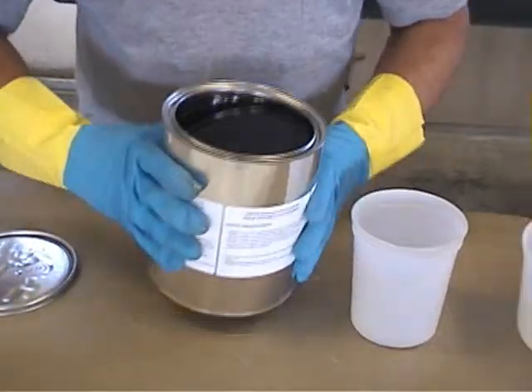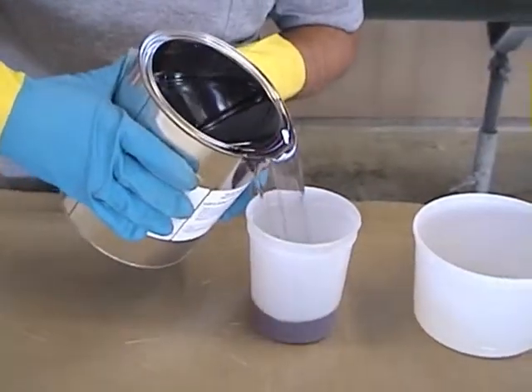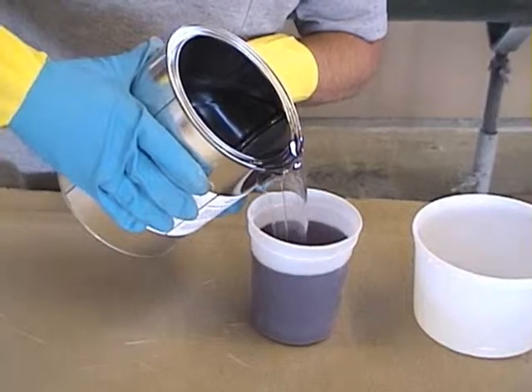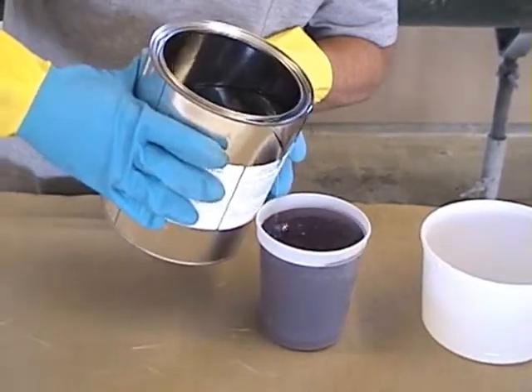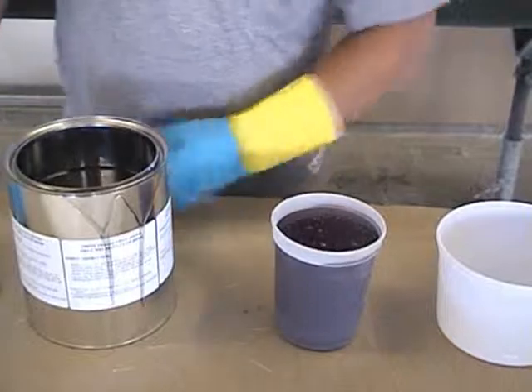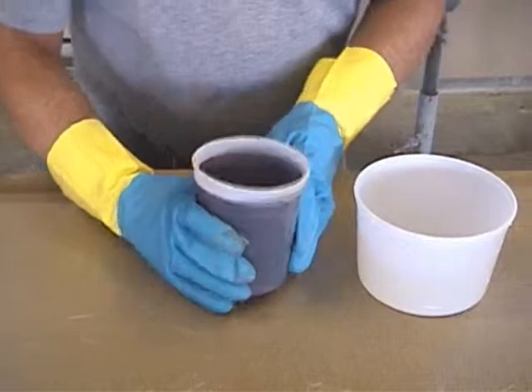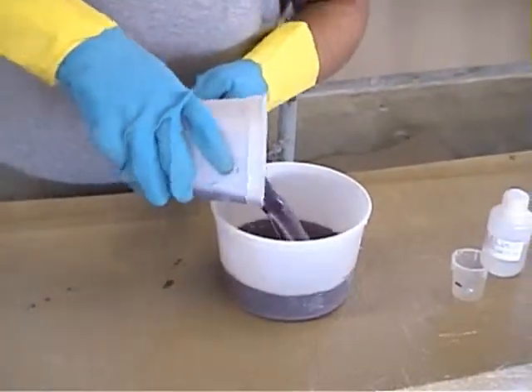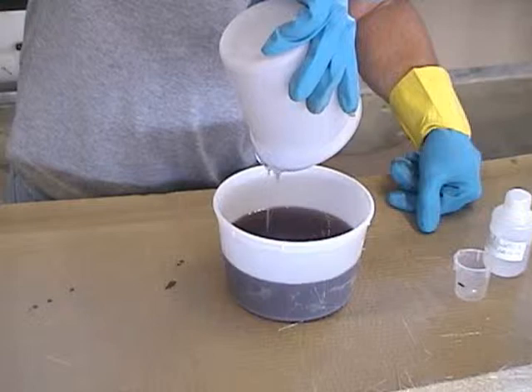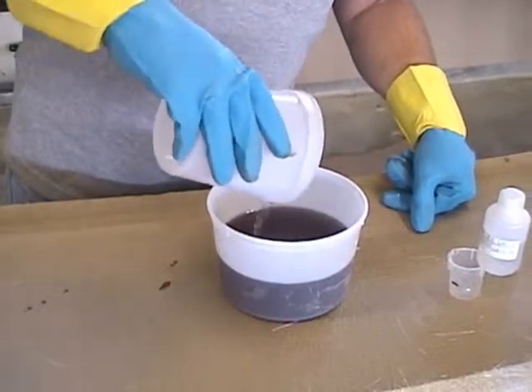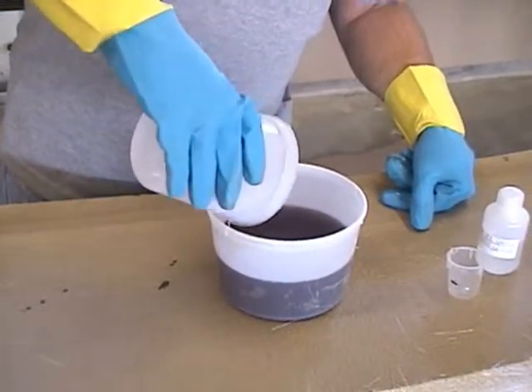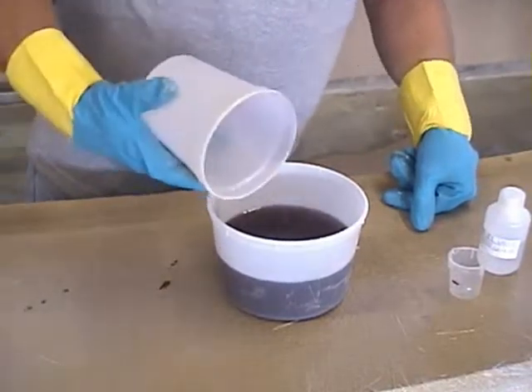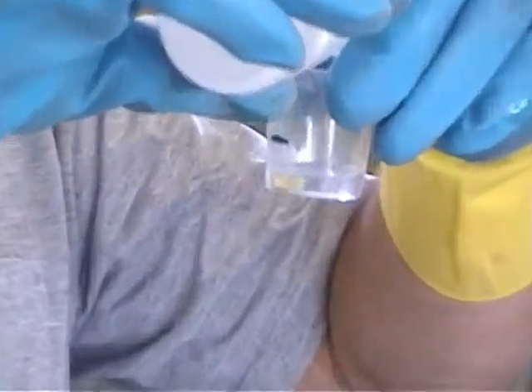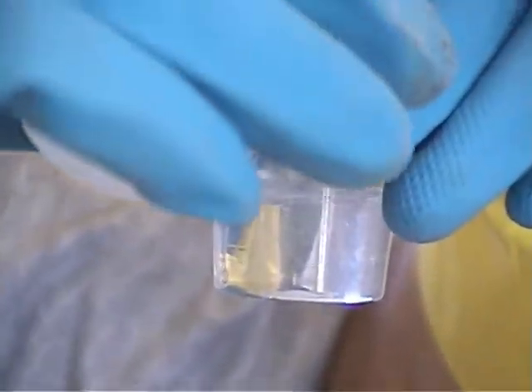Whenever you mix your resin, remember that resin is based on quart quantities. Check your instruction sheets that match the particular type of butt wrap you have so you know what type of catalyzation ratio you need. We measure a quart of resin and put it into the mixing bucket. Again, check your instructions for the mixing instructions. For this particular resin grade, the catalyzation ratio is 13 to 22 milliliters of catalyst per quart of resin. It's also very temperature sensitive, so we'll measure about 16 milliliters, about halfway between 13 and 22.